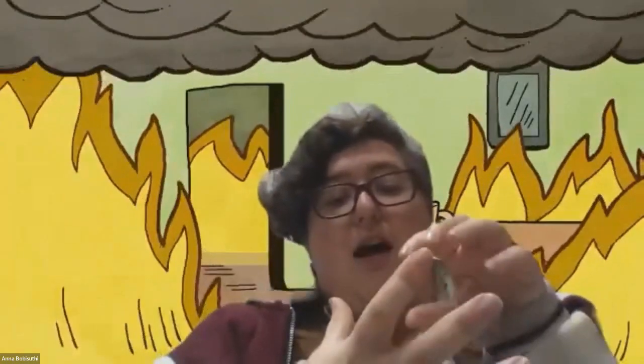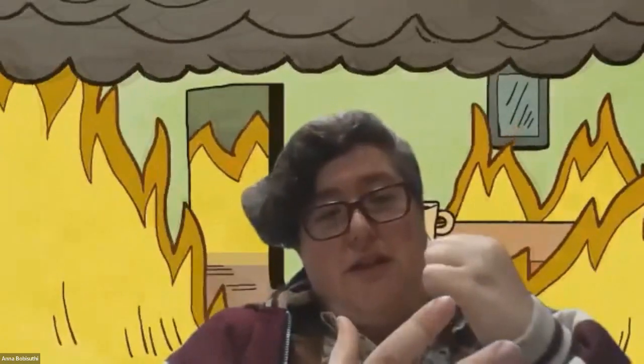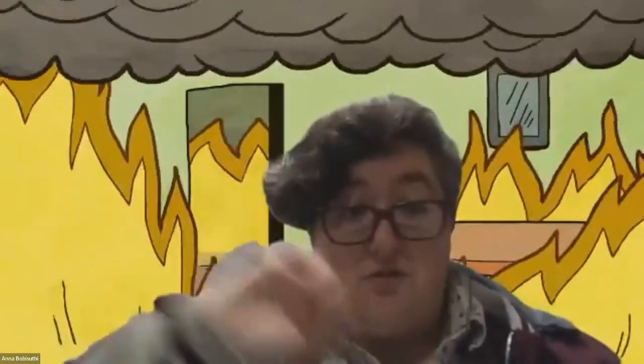About the saltwater etching technique: I have a power supply — you can also do this with batteries, a DC power supply, AC power supply, or a battery charger that's not a smart charger. You basically hook one alligator clamp to your steel and the other to a piece of metal with a wooden handle. Put paper towels or felt on it, dip it in salt water, and put it on the steel and it etches it. I do vinyl masks to get great designs. Make sure you scrub it with Windex or something afterwards so it stops rusting.